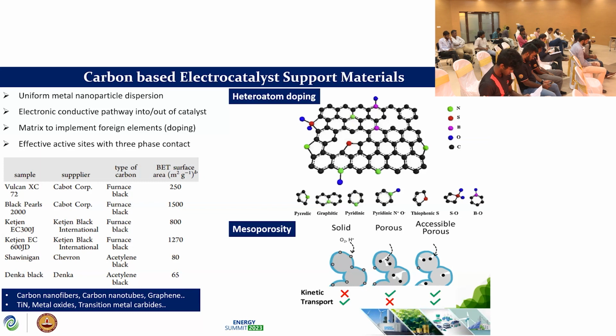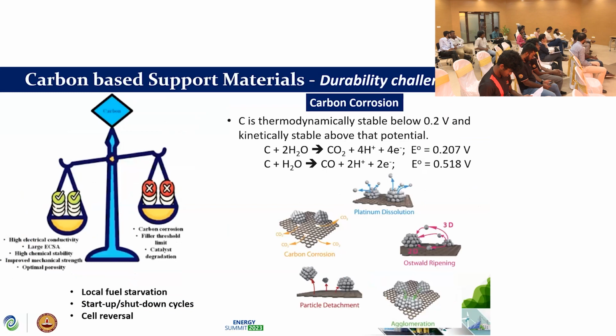However, we have to understand that if we are able to introduce easily accessible porosity into this kind of carbon support materials, we can improve both kinetics as well as the transport properties in the catalyst layer. So although there are many advantages of carbon, like high electrical conductivity, a large electrochemical surface area and good chemical stability, there are some inherent issues with these materials, like carbon corrosion. That is one of the serious disadvantages of carbon-based materials.